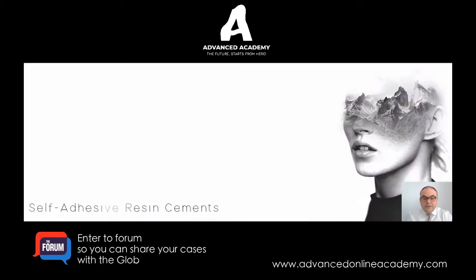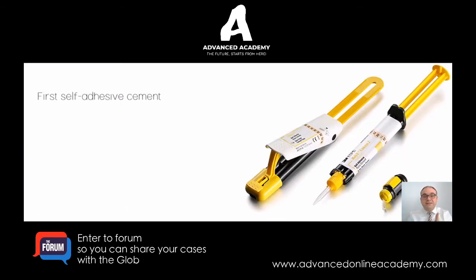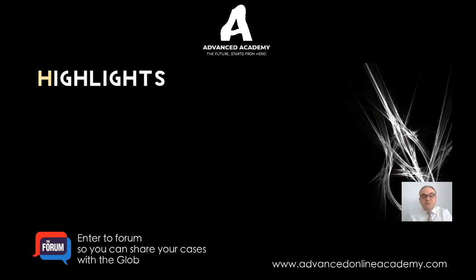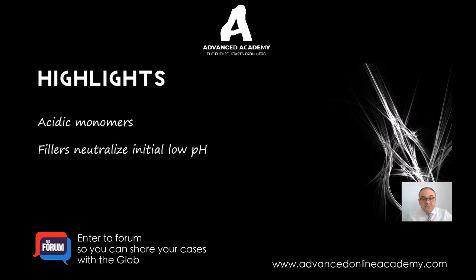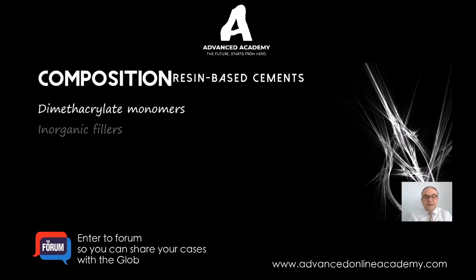So let's talk about self-adhesive cements among the dual cure cements. The first self-adhesive resin cement was RelyX Unicem from 3M. It is the most researched self-adhesive cement. These cements have fillers that neutralize the initial low pH, and they have a dual setting mechanism. It's a dual curing resin cement. So it's formed of dimethacrylate monomers, just like we said before, inorganic fillers, an initiator, and silica.